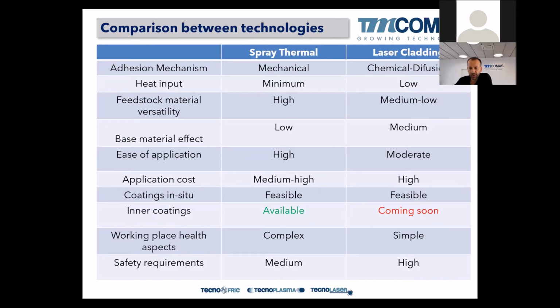Feedstock material versatility. In thermal spray it is higher, while in laser cladding it is medium to low. And that's because laser cladding is a welding, and we cannot weld ceramics, for example. We can braze them, but we cannot weld them. So all the ceramics are just sprayed by thermal spray and not applied by laser cladding.